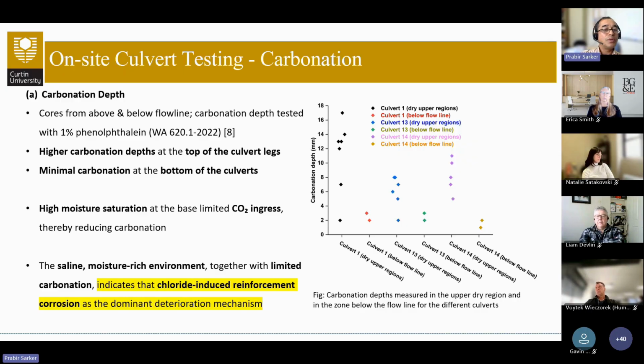Looking at the carbonation, we can see it was not the dominant type of durability deterioration mechanism. Instead it was basically chloride induced reinforcement corrosion, as indicated by the very high salinity and moisture rich environment with limited carbonation.